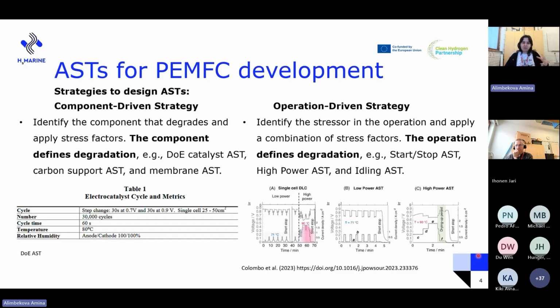These conditions severely accelerate the carbon support corrosion, the structural collapse, and subsequent electrochemical surface area loss caused by platinum detachment. It could also be done under low relative humidity to further exacerbate the conditions.